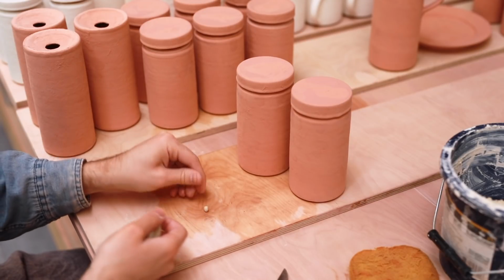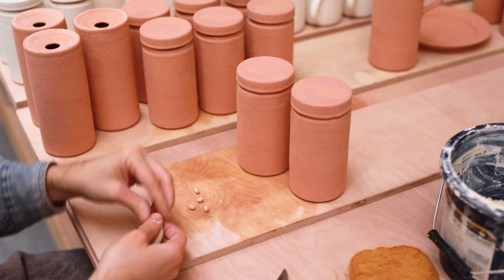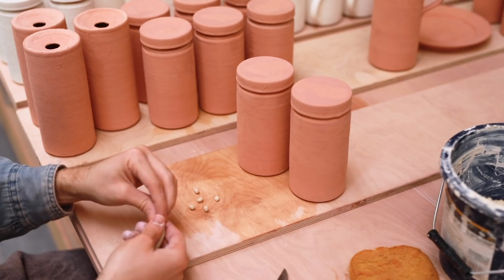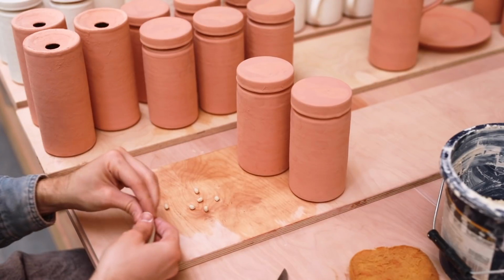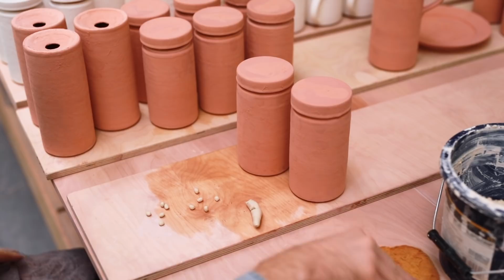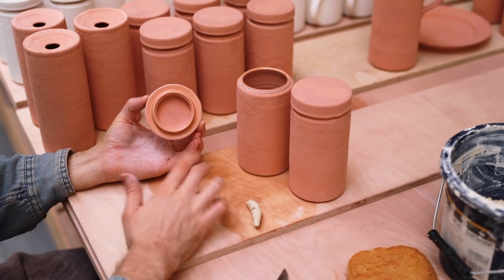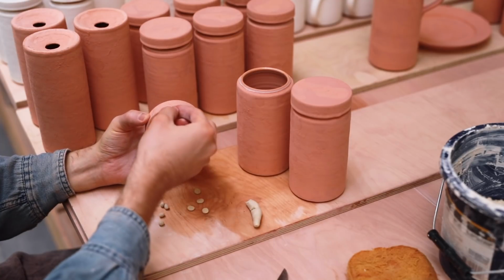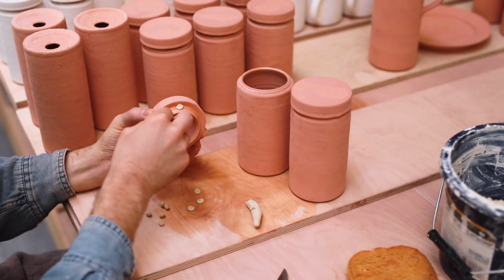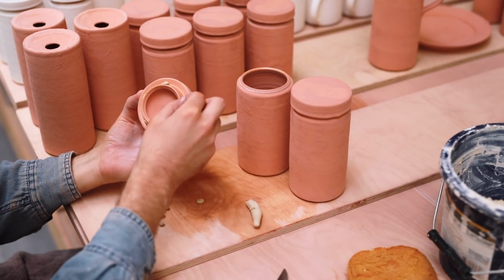But all of my lidded vessels, like you see here, must have their lids propped up using these tiny balls of wadding. This material is made up from 50% china clay and 50% coarse alumina hydrate, although there are endless recipes out there. I wedge the stuff up into a clay-like consistency and carefully press each ball into a little disc, which I then position around the gallery of the lid, like you see here.